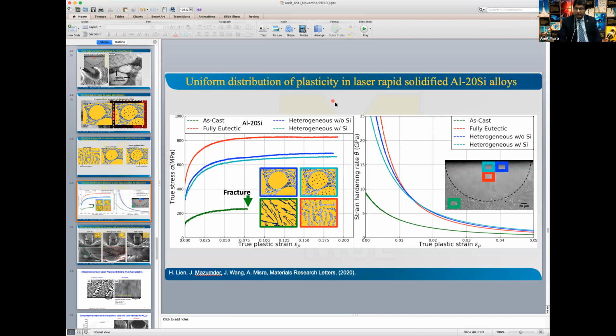I have not seen it. Others maybe have seen it, but we have not. If you define Hall-Petch strictly as 1 over square root, that 1 over square root scaling law tends to break down. The strengthening continues. The scaling law changes, but then you reach some kind of saturation. Below that, what you see is subject to interpretation.